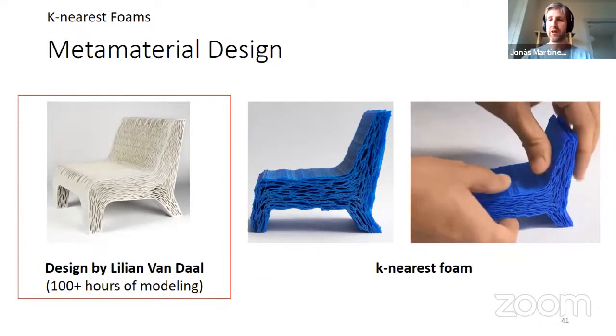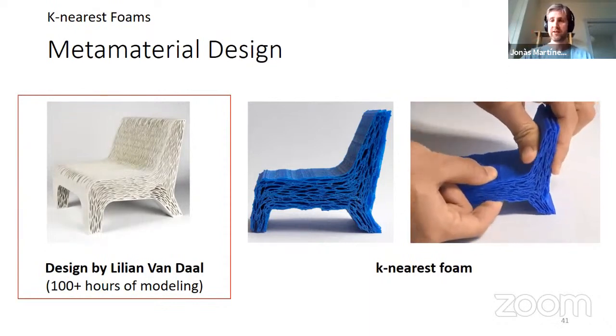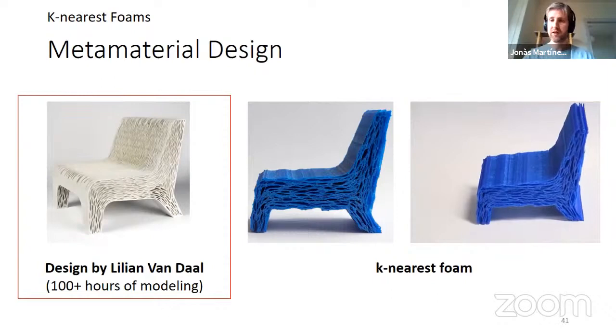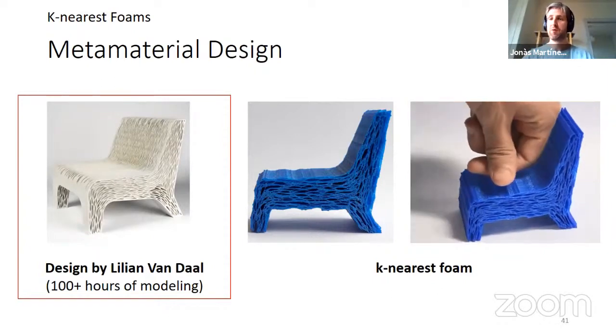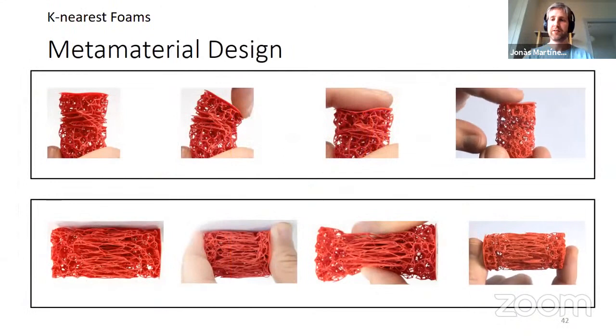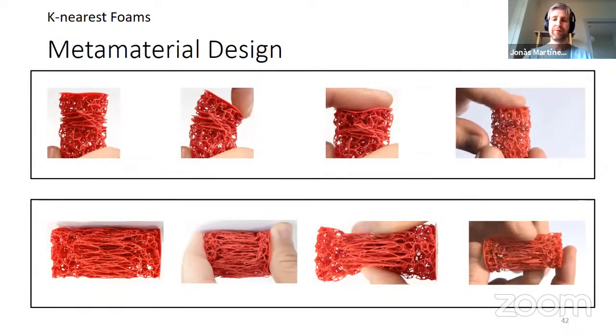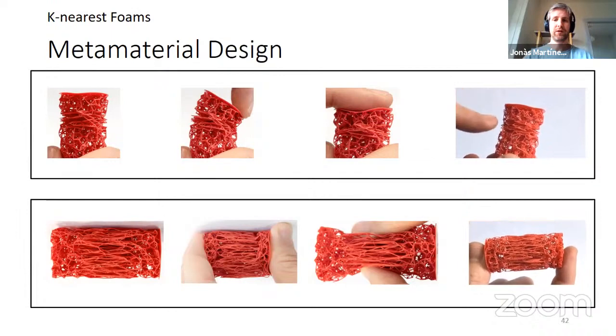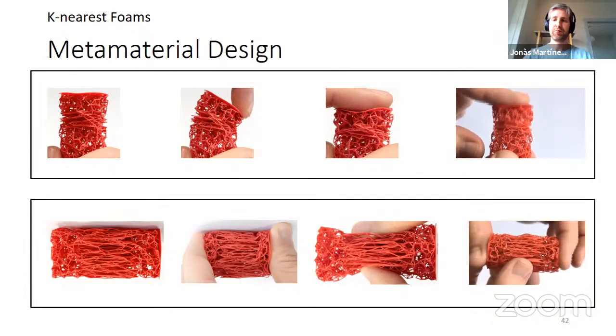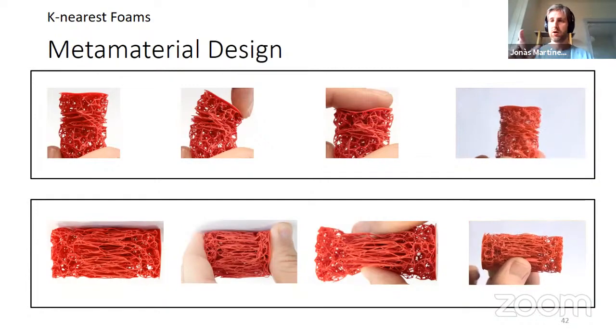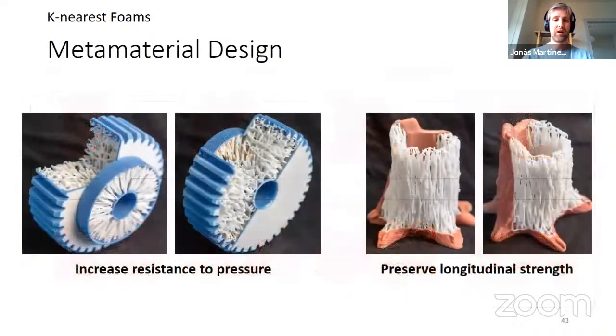And on the contrary, with our foam, just by rapidly aligning the fibers, we can get similar results. We can also get interesting results due to the fiber alignment. Here you can see cylinders with different properties depending on where you compress them. And of course, you can also envision using these materials, for instance, to increase the resistance by aligning the fibers to the direction of pressure and so on.